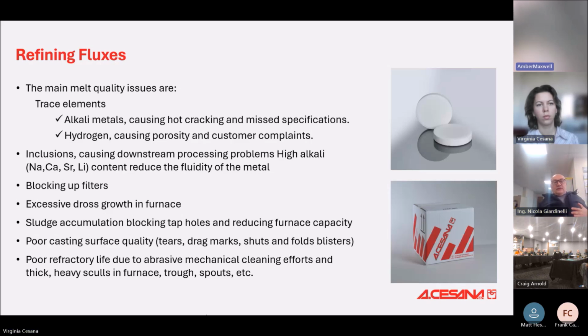Refining flux. During the melting, we can have a few impurities and inclusions inside the liquid metal, also alkaline elements. The big problem of the alkaline elements is that they can cause hot cracking during solidification. The second problem is hydrogen. Metal with a high percentage of hydrogen means porosity in the final parts.